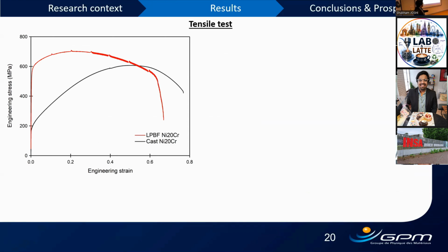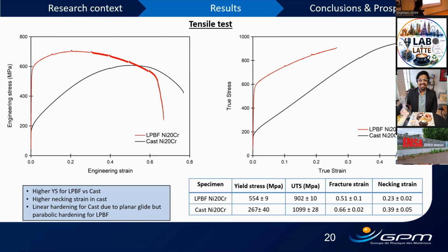On the left, you can see the engineering stress strain curve for LPBF in red and cast in black. And in the true stress, true strain framework, the same curves can be seen. There is a lot of data, and it's interesting, but right now, only two important messages you need to keep in mind. If you look at the yield stress of the LPBF sample, it's more than double that of cast, and the strain hardening behavior of LPBF somewhat looks like parabolic hardening. But when we compare it with cast, we have a long linear hardening.